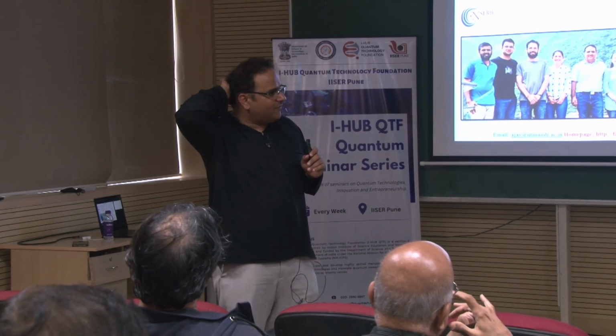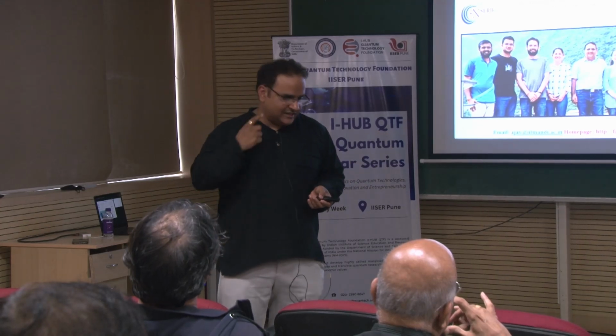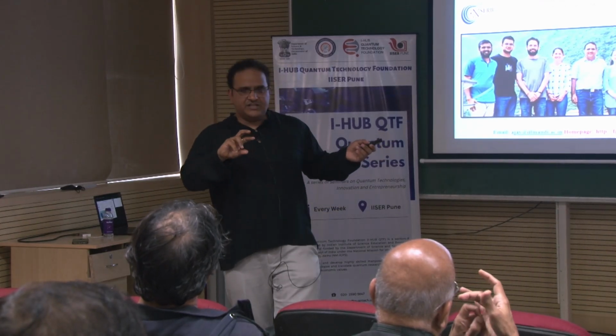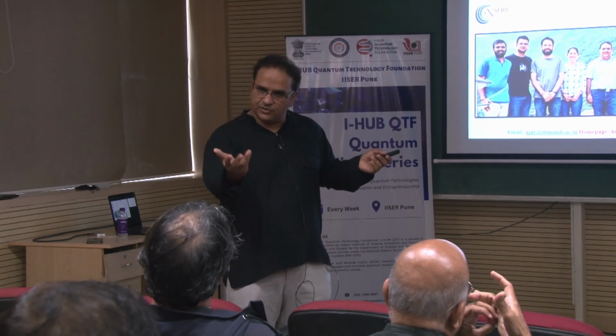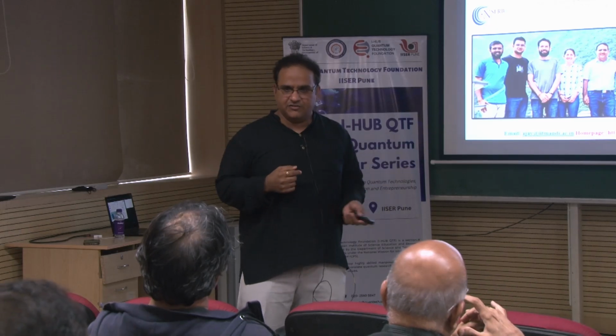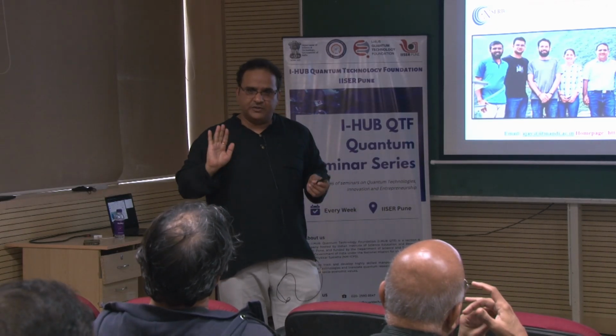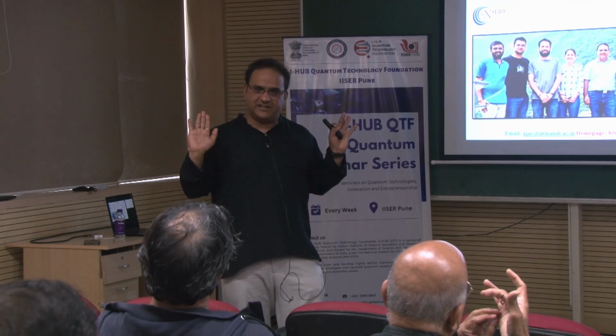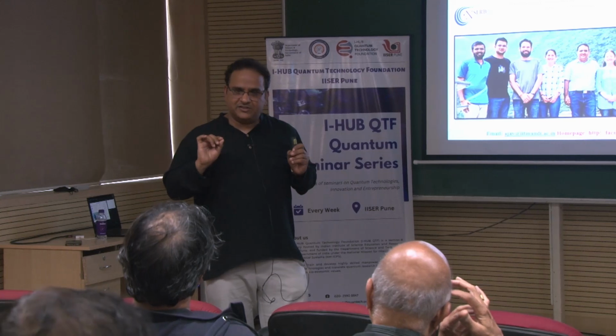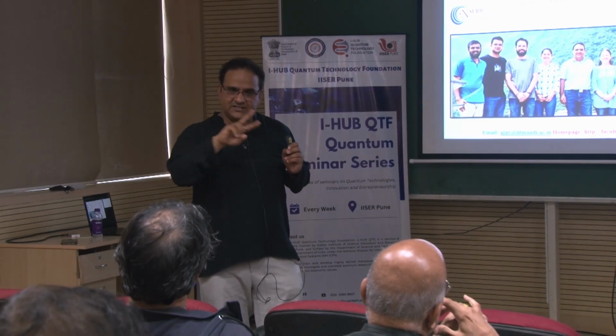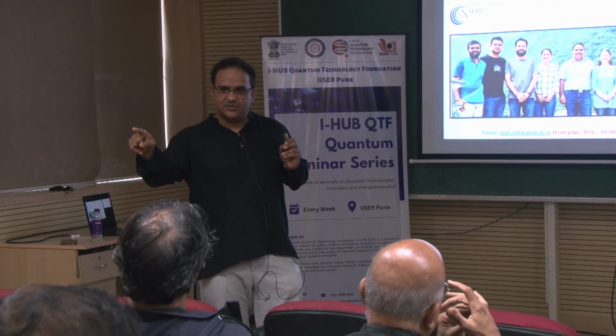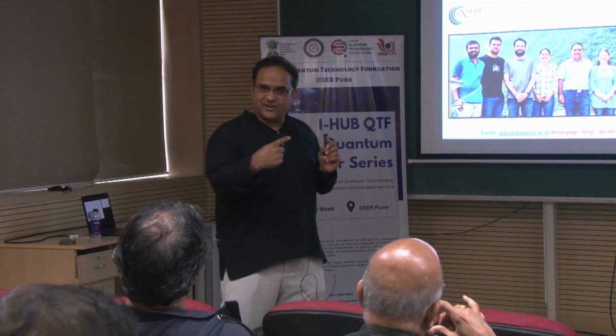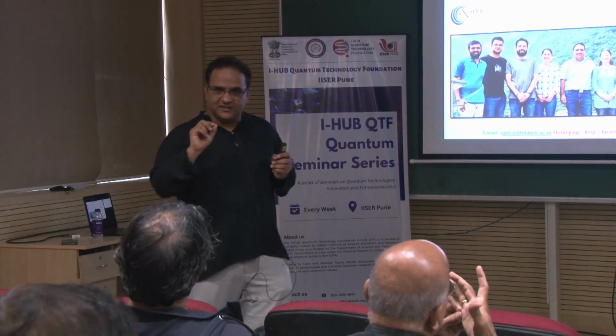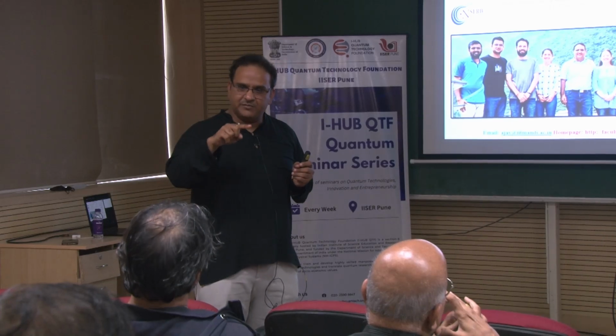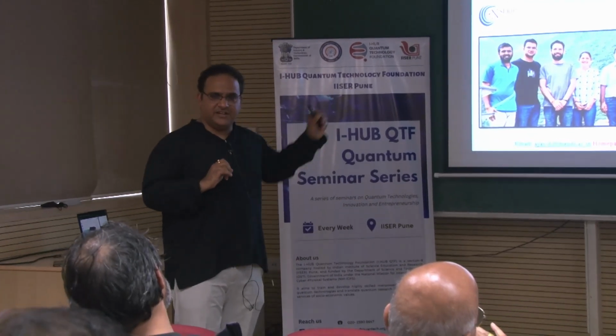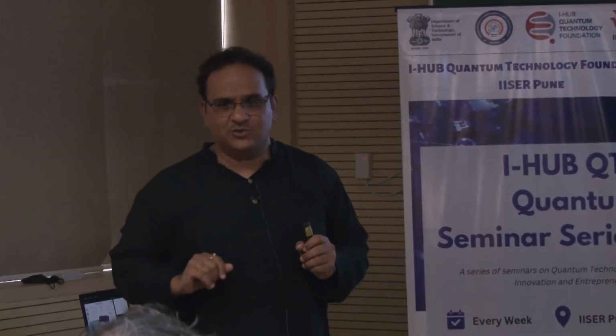Of course, in Raman we will be able to get new modes, and not only that, the moment you change the symmetry, like the center of inversion symmetry, you get new modes, which we have seen in tin telluride, which I have not shown here. Tin telluride is a cubic system, you do not expect Raman spectra from it because it is symmetric. We put Mn into it. The moment you put Mn into it, because of the different ionic size, Mn is replacing Sn. So now you are changing the center of inversion, and at low wave number, I wish I could show the data, we have found new modes which are coming because of the breaking of the symmetry. So the symmetry breaking will give you new modes if the material has those modes.